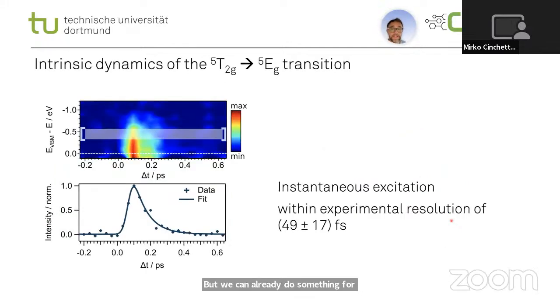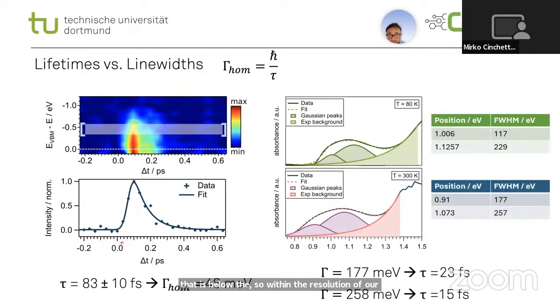For example, we can have a look at the time scale of the relaxation. First of all, we see that the excitation is more or less instantaneous. Instantaneous in this case means within the resolution of our experiment, which is 50 femtoseconds. Then we can also have a look at the lifetime of this excitation. And here we find a surprisingly short lifetime of 83 femtoseconds, which is actually unexpectedly low for a localized atomic-like transition. And this gives us an indication that the hybridization between the iron bands and the sulfur and phosphorus bands, although minimal, must be considered to fully understand the relaxation dynamics of these excitations.